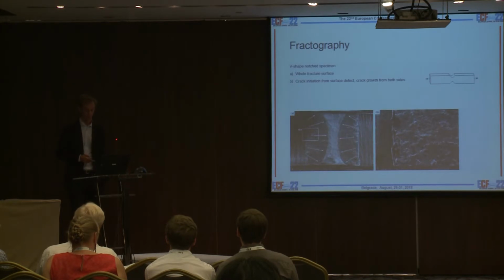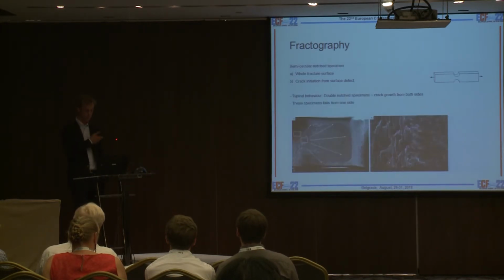the crack initiation area. So for the semicircular specimen, the crack is propagating from only one side, which is weird when you have the double notch component. And there is also a lack of fusion defect in the surface.